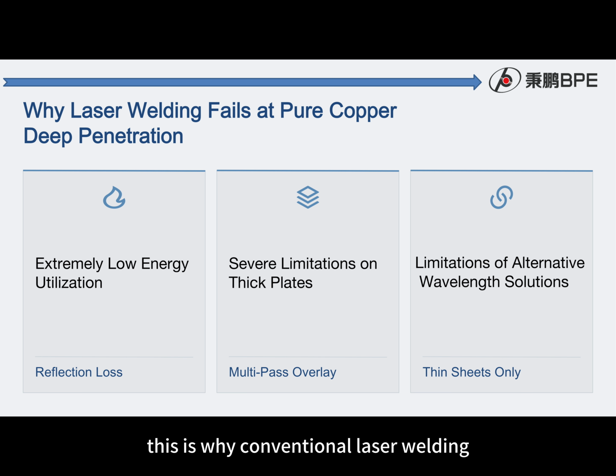This is why conventional laser welding struggles with deep penetration. Most infrared laser energy is wasted, and reflected beams can damage expensive optics. Cranking up the power leads to massive heat buildup, severe distortion, and coarse grains. Multi-pass welding on thick plates is slow and prone to porosity. Even green or blue lasers, while absorbed better, are power limited, expensive, and mostly stuck on thin sheets.